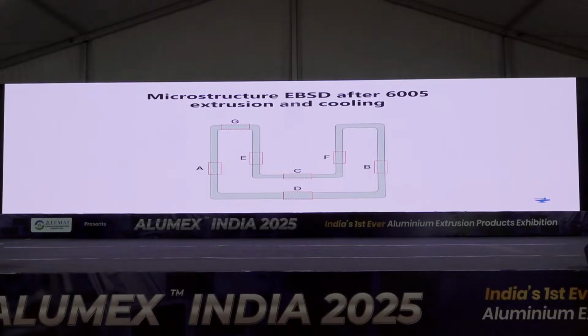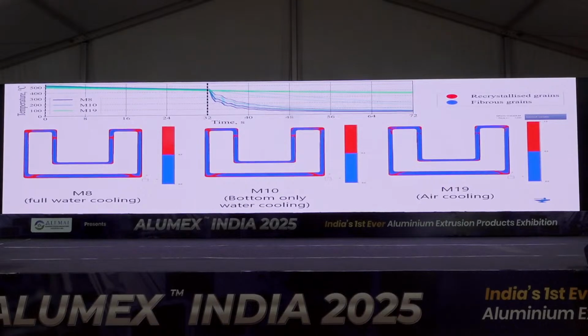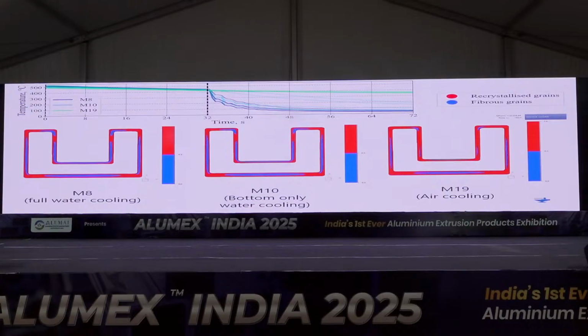Here you can see different regions of the profile where microstructure samples and eventually EBSD diagrams were obtained. And here you can see the results. So here you can see three different conditions of cooling and the prediction of the so-called PCG, or peripheral coarse grain layer, which will obviously be different depending on the cooling rate. And here you can see different cooling rate graphs. At the top, M8, M10, and M19 just refer to different cooling rates.